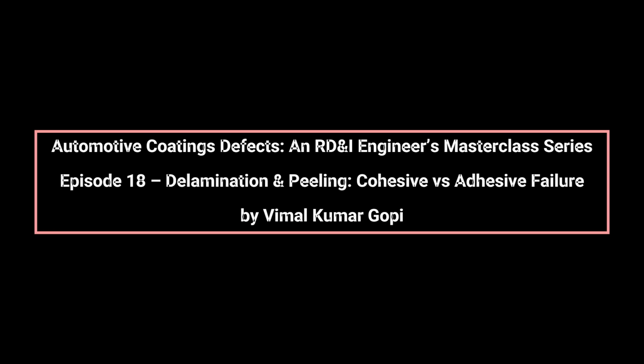Adhesive failure indicates insufficient bonding between layers or to the substrate. Common causes include low surface energy, contamination, improper flash-off, missed recoat windows, or incompatible chemistries between layers. In many OEM cases, adhesive failure is linked to surfaces that looked visually perfect but were chemically inactive. Fully cured or oxidized surfaces resist solvent swelling and polymer interdiffusion, preventing proper bonding.